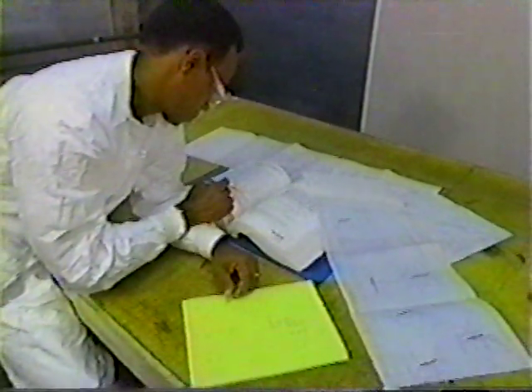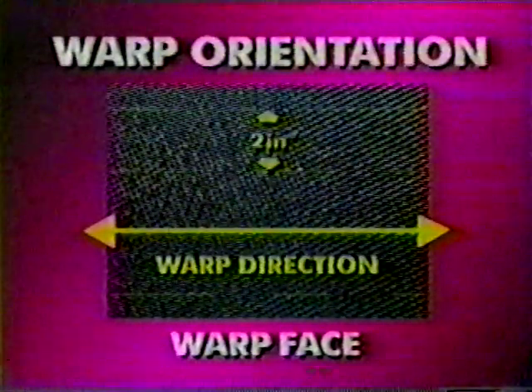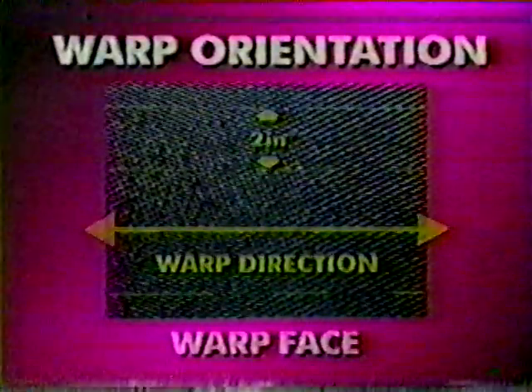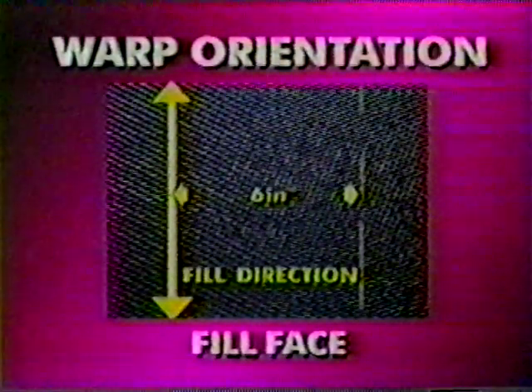Before cutting the materials to complete the repair, you must first consult the structural repair manual or the engineering drawings to make certain the warp orientation of each ply matches the rosette pattern specified in these documents. To identify the warp orientation of the graphite material, some manufacturers have included yellow tracer strands of Kevlar, approximately 2 inches apart, to identify both the warp direction and the warp face of the material. On the opposite side of the material, tracer strands of Kevlar run 90 degrees to those on the warp face and are 6 inches apart. This identifies both the fill direction and the fill face of the material.